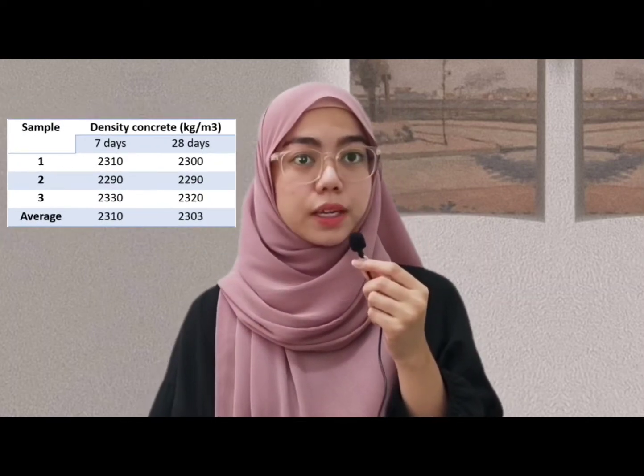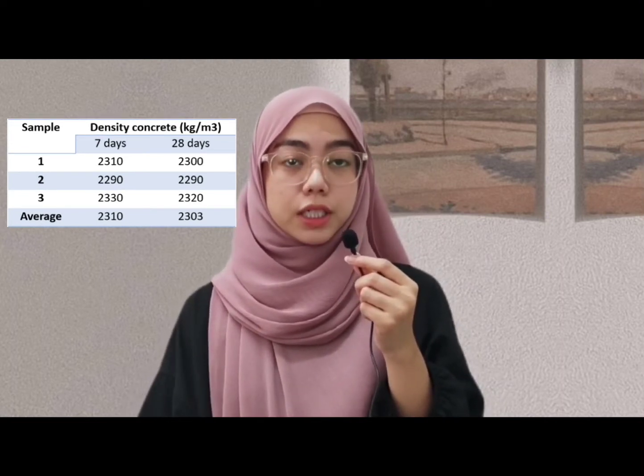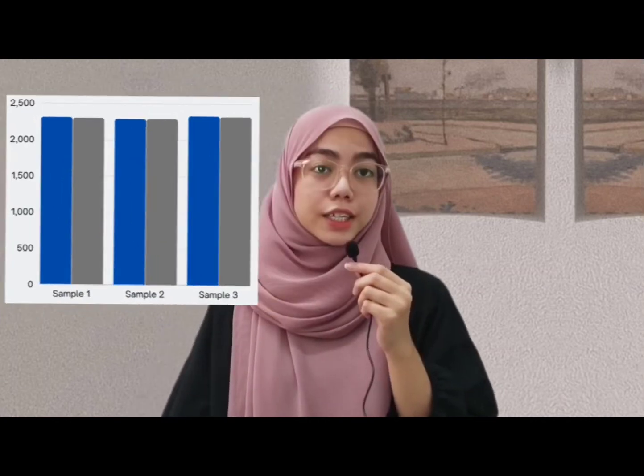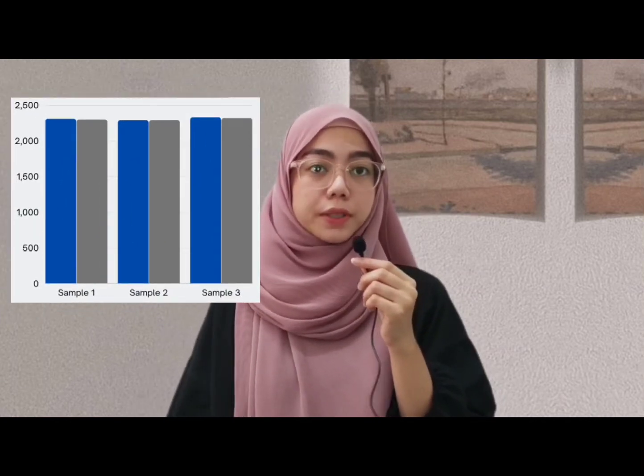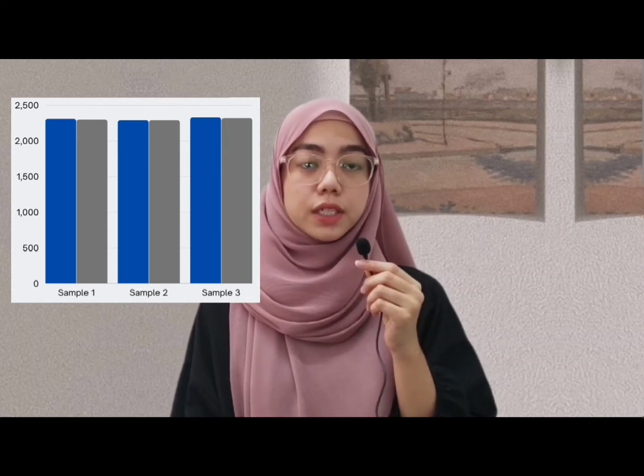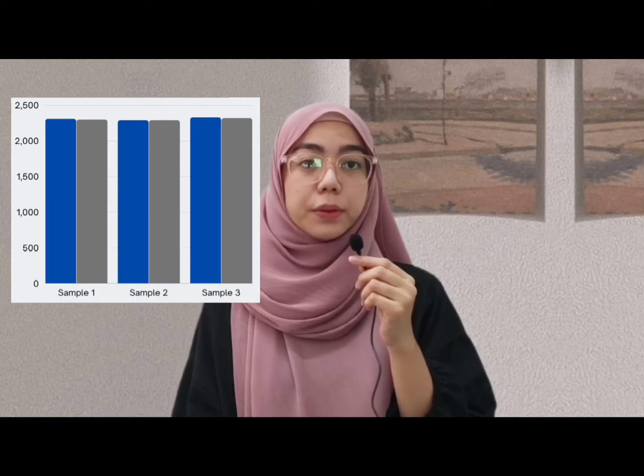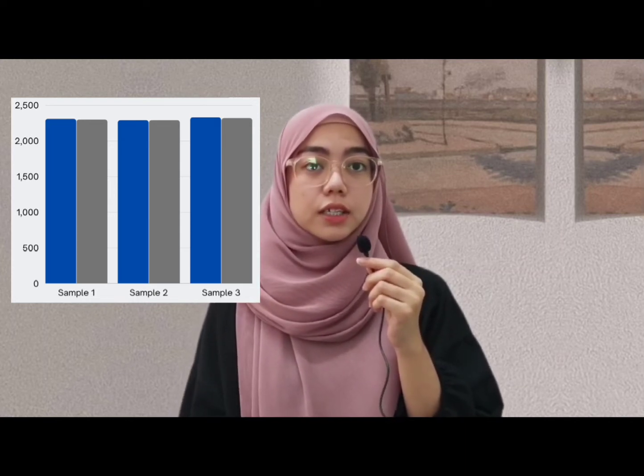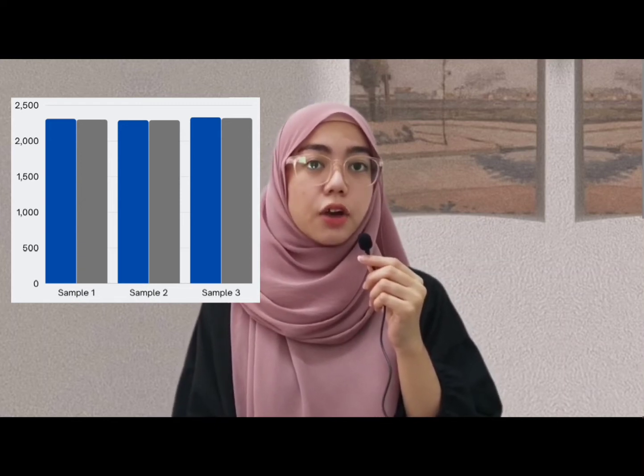In this chapter, the density of concrete has also been discussed. As you can see, the table and the graph are from the data of the concrete samples for the density of concrete from 7 days and 28 days of curing. From the data obtained, we get to know that the density of concrete is directly influenced by the curing days. The graph shows that at 7 days curing, sample 3 has the maximum density, which is 2,330 kilograms per meter cubic, and the lowest density is from both curing days, 7 days and 28 days, for sample 2, which is 2,290 kilograms per meter cubic.